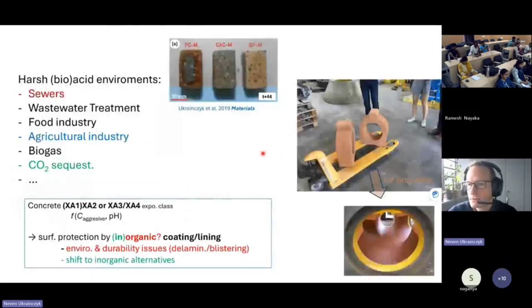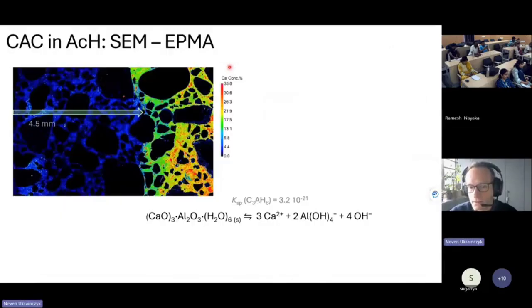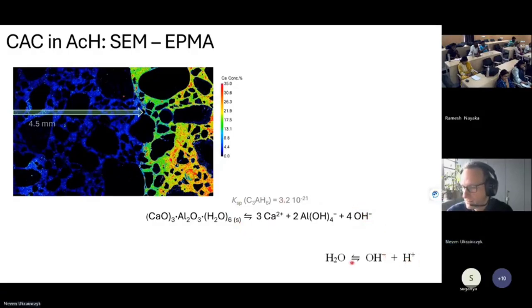Yeah, it's one of those samples here, but for aluminate cement, acetic acid strongly dissolves aluminate cement, which should be acid resistant, but because of these complexation reactions, it dissolves a lot of calcium. And now you know the mechanism. Again, the equilibrium constants are important, because you can see here OH minus. So this is the calcium aluminate product, the stable one. It has a solubility product, which should be constant. And if you are taking this OH minus away because of the acid, you are removing the OH minus. That's why you increase the solubility. And that's the mechanism of the acid attack.